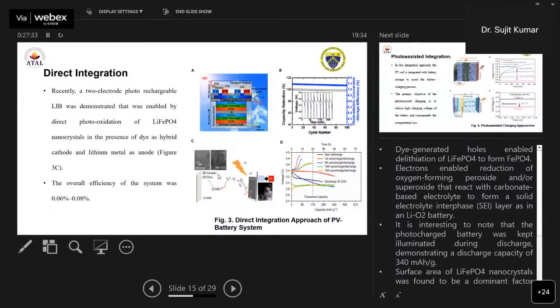Okay, that means they can use the direct photo oxidation of lithium iron phosphate nanocrystals in the presence of dye as a hybrid cathode and the lithium metal. So here the overall efficiency of the system was around 0.06 to 0.08 percent. So what happened in this particular case is that the lithium iron phosphate nanocrystals in the presence of dye, this dye generated a number of holes that enabled the delithiation of lithium iron phosphate.